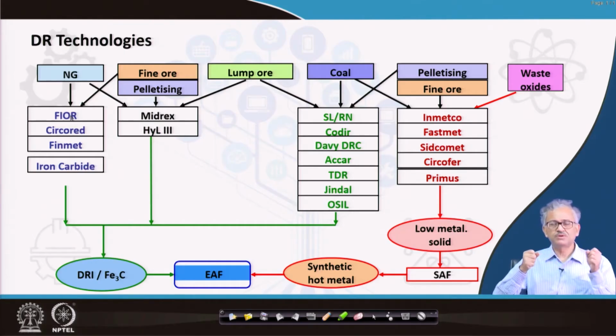The only difference is this. First let me tell you about the FIOR process. In the FIOR process you have fluidized bed reactors in series, around 4 or 5 reactors, and in the first reactor some preheating is done by burning natural gas. Then the 3 reactors in series reduce it. The reducing gas, which is reformed natural gas, enters through the last reactor and then cascades through the other reactors. In the Finmet process, the only difference is that the preheating is done by the off gas from the reduction unit. In FIOR natural gas heating is required, but here you recycle the off gas to preheat the material, and some other process variants may be there. Otherwise both are fluidized bed reactors.